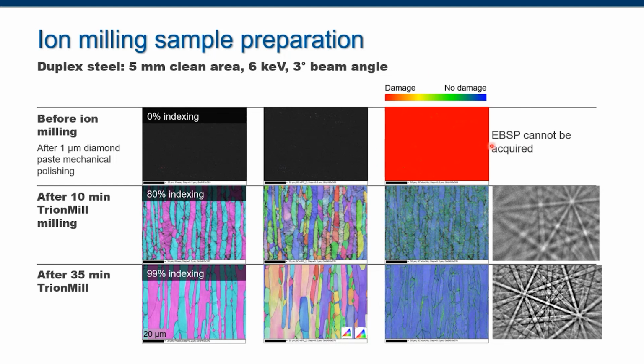in red. After 10 minutes of TrionMill, one of our systems, you will get up to 80% indexing. You will start to distinguish the phases present in your material, but still you will see that damage on the surface from mechanical polishing. You can see a lot of scratches, and on the local misorientation map here, you can see only the surface deformation, the surface damage. As you can see here, the EBSD pattern quality is very poor. They are fuzzy.